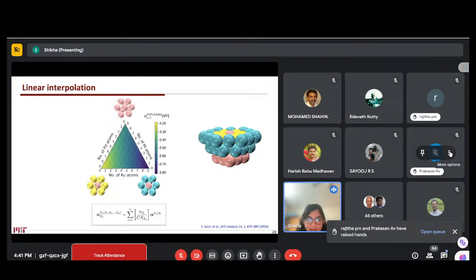Once we have the alpha parameters for the given pairs, we do linear interpolation for our ternary cases. So now we have a site with platinum, palladium, and the central site is ruthenium. Now I will randomly change the composition: any number of palladium, any number of ruthenium, any number of platinum.